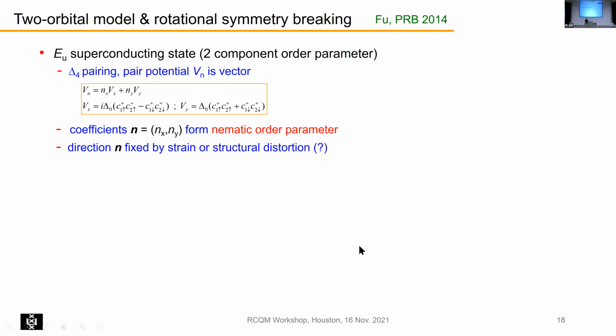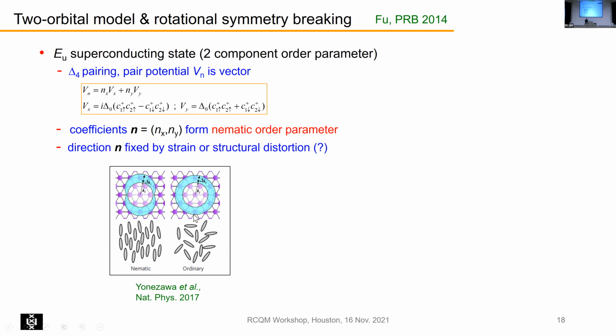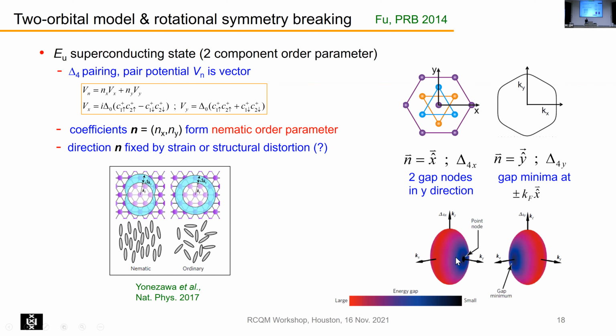So it is actually borrowed from liquid crystals, where you have these cigar molecules. If isotropic, then you have an isotropic gap. Here they are aligned along a certain direction, and your gap also has some anisotropy, and that gap is kind of pinned to the lattice, possibly because of strain. You can also make predictions then for the superconducting gaps. If this director is along the x direction, you would have 2 gap nodes in the y direction, and if it is along the y direction, you would have 2 gap minima. So you can try to look for these as signatures of these different delta 4x and delta 4y superconducting gap functions.